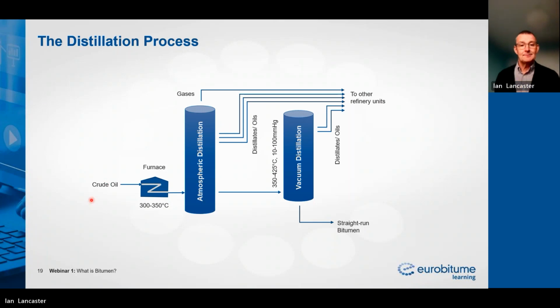So our crude oil comes in from the tank and is passed into a furnace where it's heated to approximately 300 to 350 degrees. It emerges from the furnace into the atmospheric distillation column, and the low boiling point materials rise up the atmospheric distillation column, and they could be gases, they could be light oils, distillates, kerosene, that sort of thing, and they're taken away to other refinery units. Our residue at the bottom of the atmospheric distillation column is then passed through a second furnace.